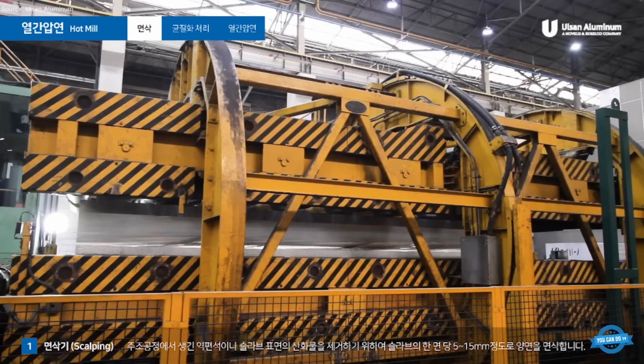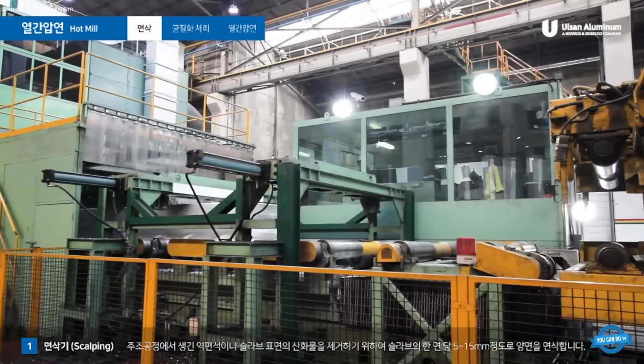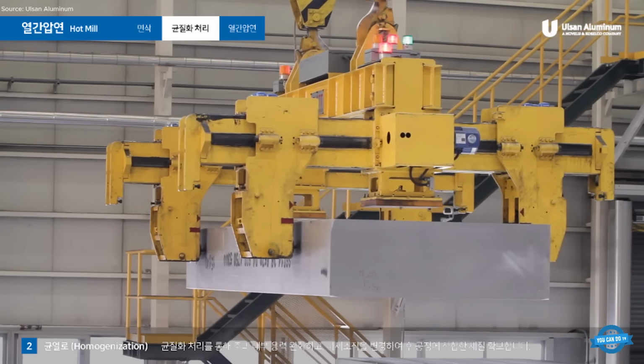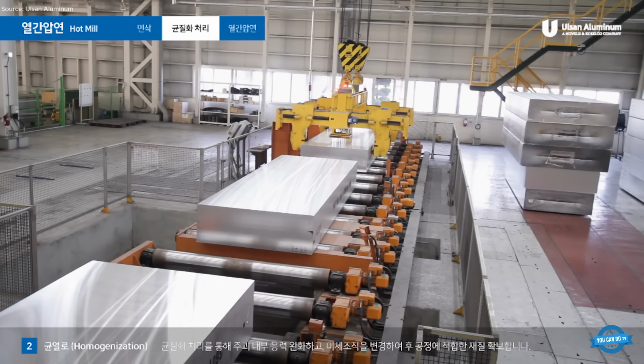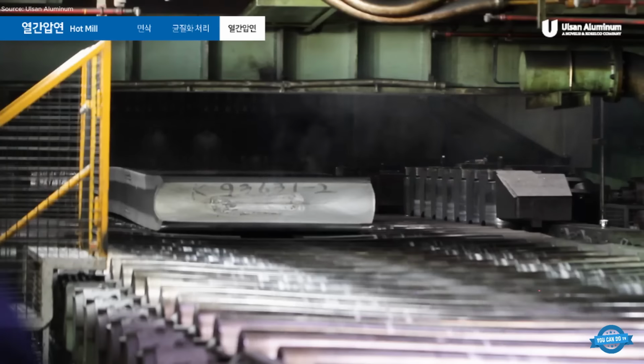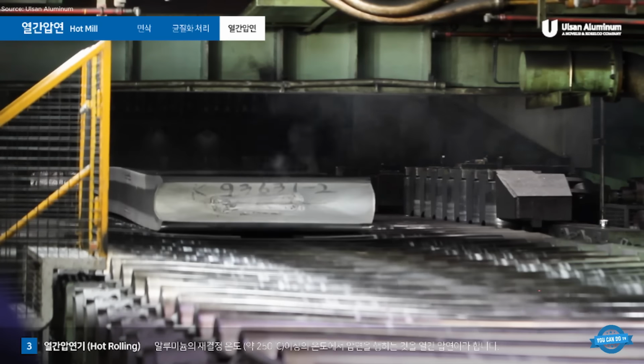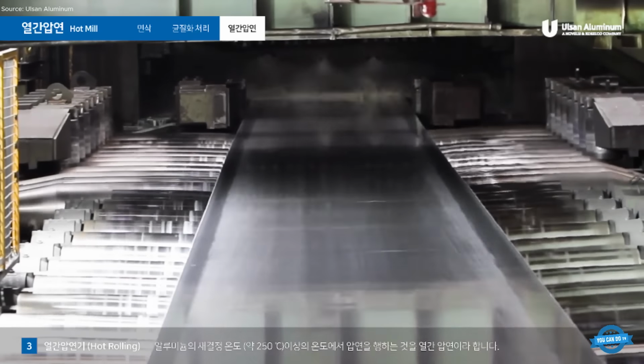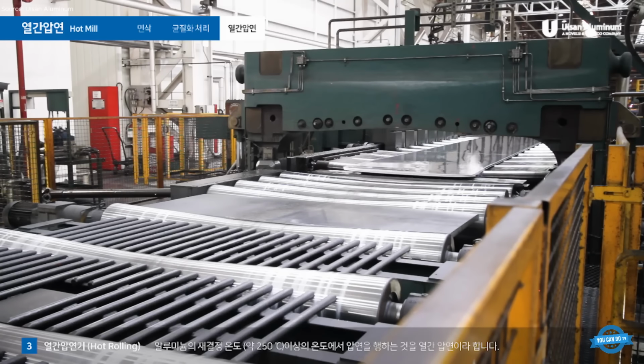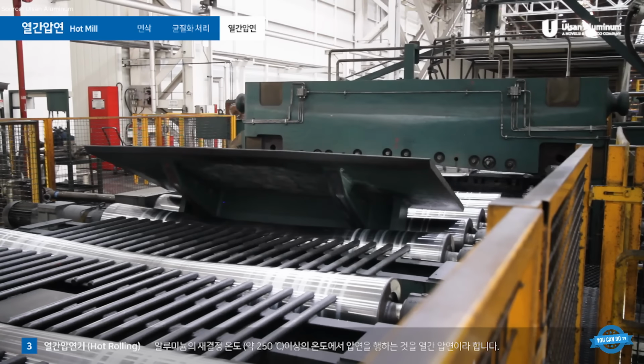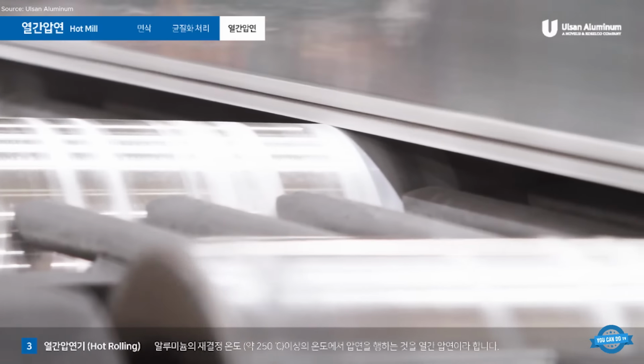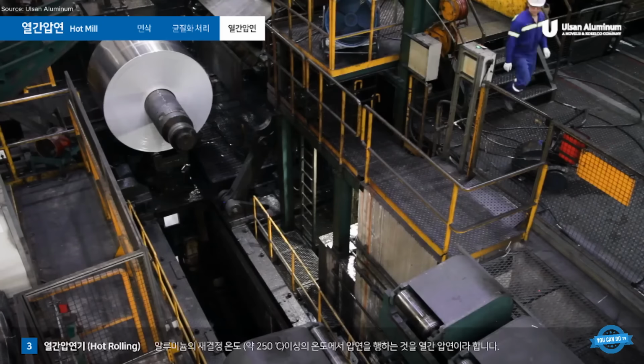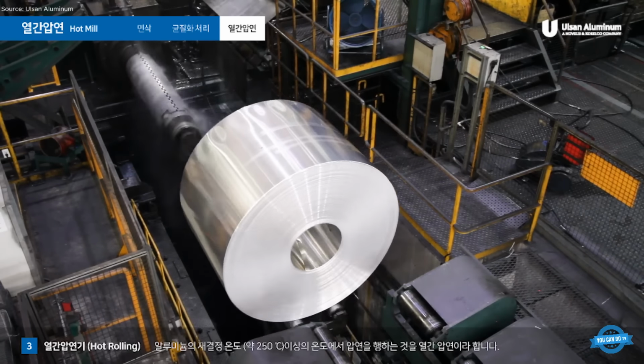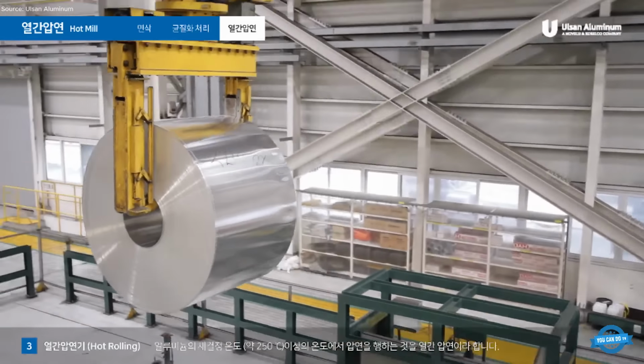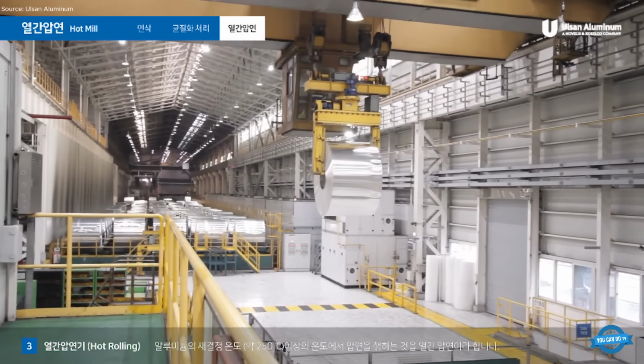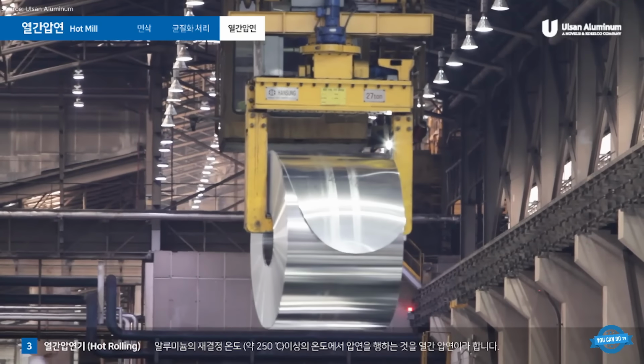Once solidified, the slabs are subjected to surface milling, a process that removes oxidation layers and impurities to achieve a clean surface. Homogenization heat treatment follows, equalizing the internal structure and improving workability. The slabs then undergo hot rolling, where they are passed through heavy mills at elevated temperatures to reduce thickness and refine grain structure. After hot rolling, the process advances to cold rolling. Here, aluminum coils are reduced further under controlled pressure to achieve precise thickness and enhanced surface quality. Degreasing treatments remove residual oils, while annealing restores ductility lost during deformation.